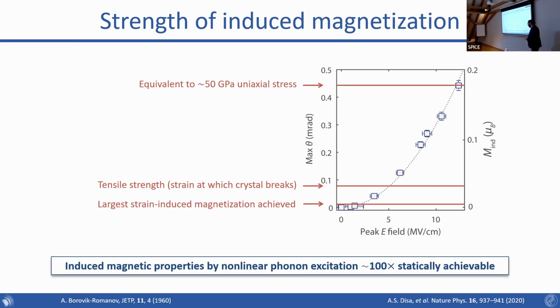This is just a consequence of the fact that we're not really applying strain, but we're doing this dynamically by driving phonons. And this would be equivalent to applying something like a 50 gigapascals uniaxial stress to the system. So something that can be in principle quite useful.